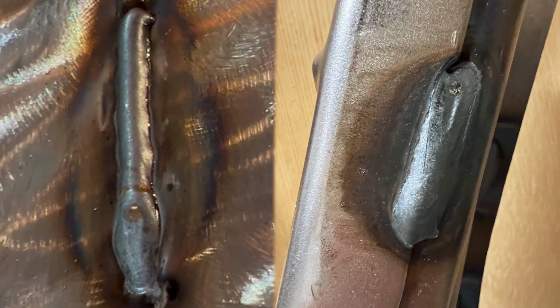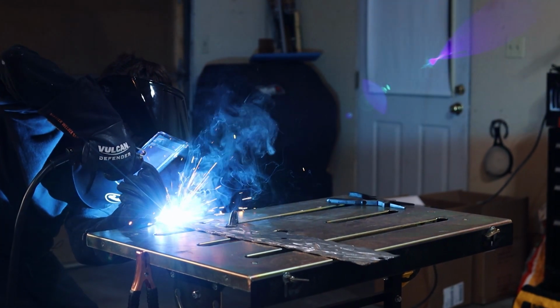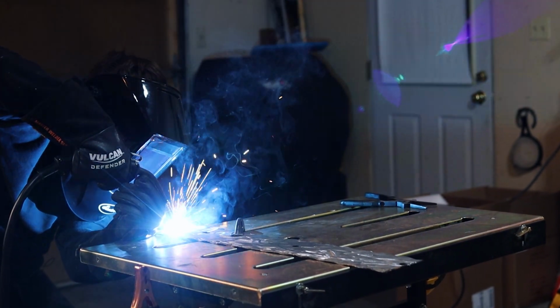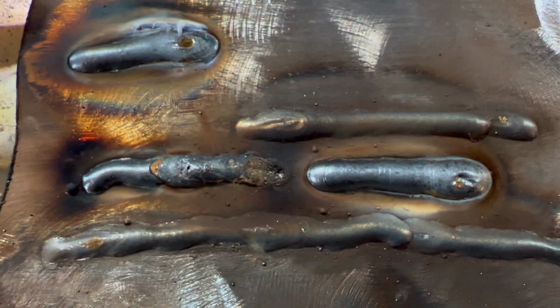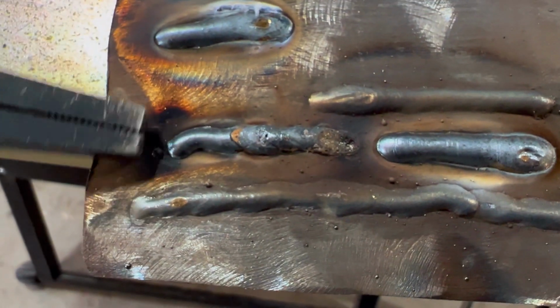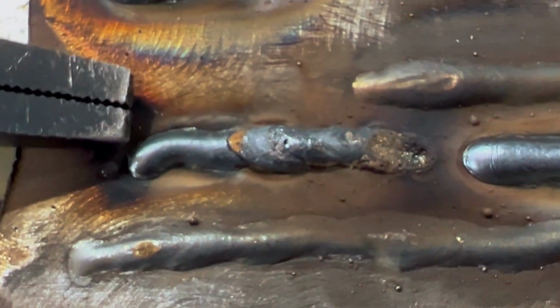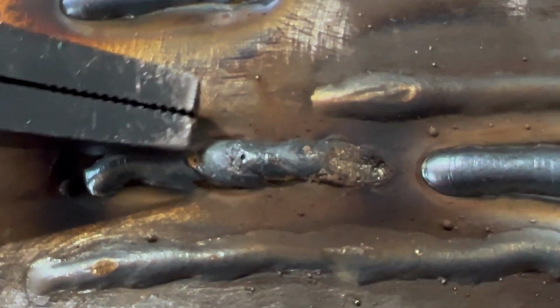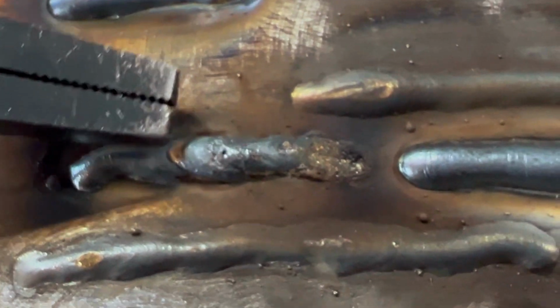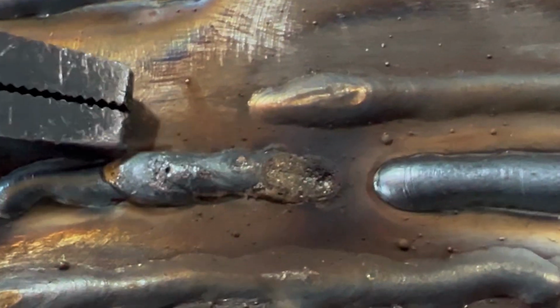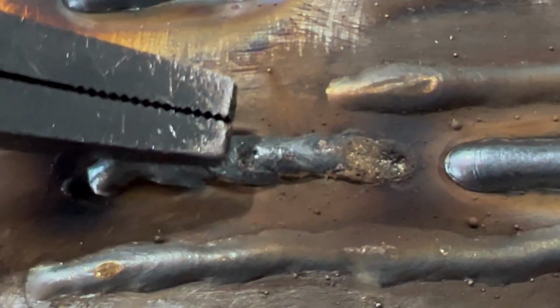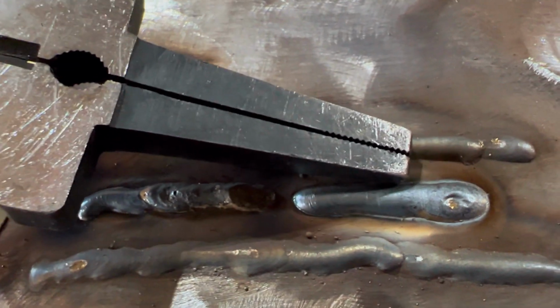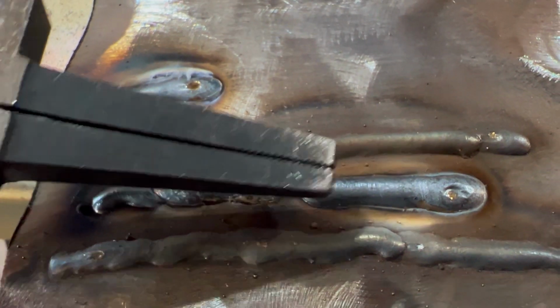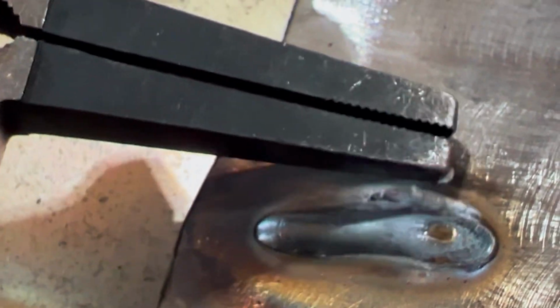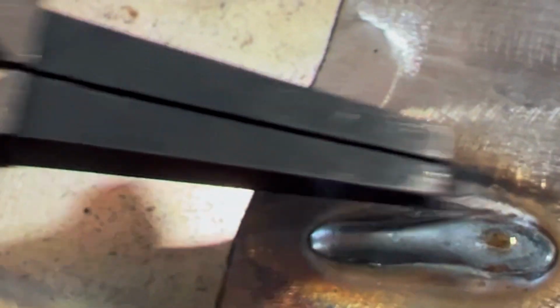On the left, we have my weld, and on the right is a Ford factory weld. I did a few more beads, and I actually forgot to turn the gas on when I started, but it had a little bit of gas up until this point, and you could really tell it just sounded awful. And look at the quality of that weld. It's got all kinds of porosity. I went a little bit slower, and it looks pretty darn good right there. No idea what this white stuff is. It's very strange.